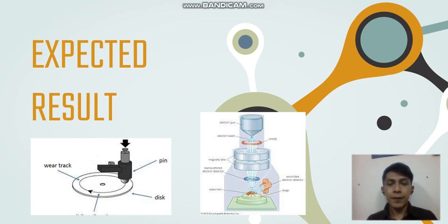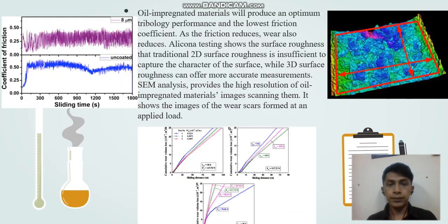Then for the expected result, we have done the three tests, which are pin-on-disc testing, Alicona testing, and SEM analysis. I expect that oil impregnated material will produce an optimum tribology performance and the lowest friction coefficient. As the friction reduces, wear will also reduce. Then Alicona testing shows the surface roughness, where traditional 2D surface roughness is insufficient to capture the character of the surface, while 3D surface roughness can offer more accurate measurement in images.